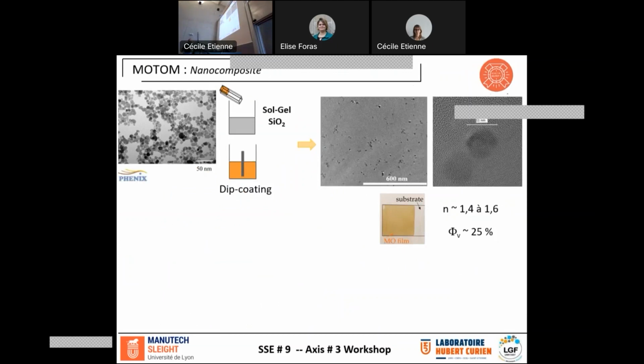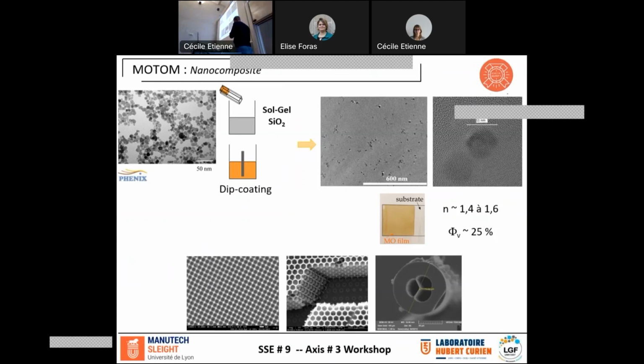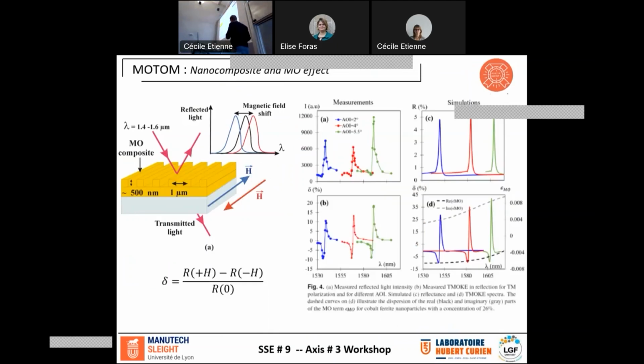The volume fraction of nanoparticles can go to 20, 30%. And we were able to realize a two-dimensional microstructure, a three-dimensional one, and we were also able to fill an optical fiber, a microstructured optical fiber, in order to obtain a magnetic functionality in that kind of fiber. For example, we have done that kind of device.